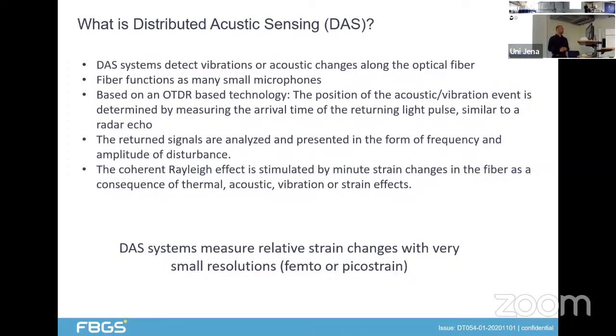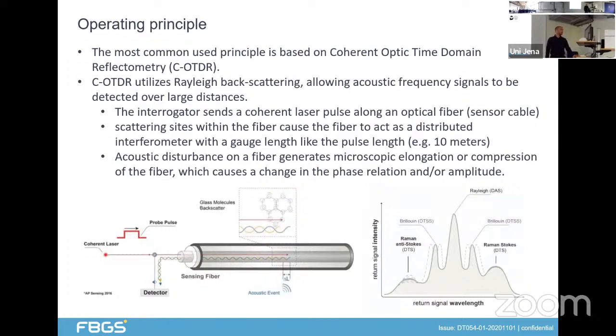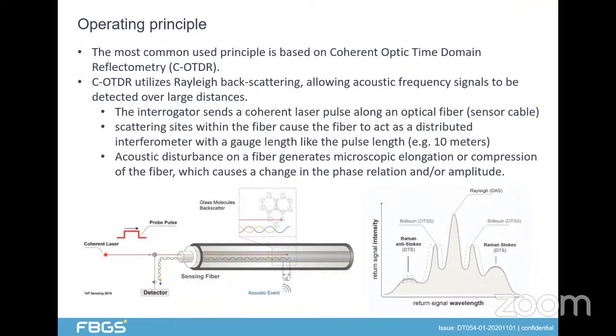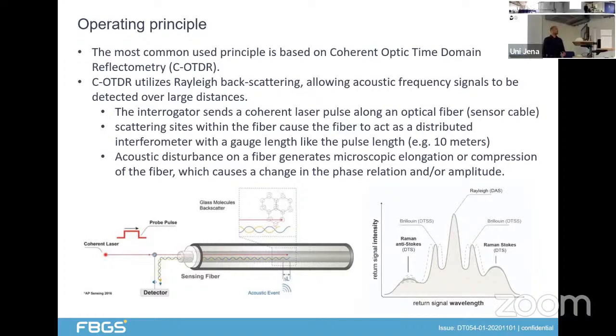The good thing about DAS systems is that they have really small resolutions. They can pick up strain, so changes in the fiber, in the range of femto or picostrain. On the other side, it is hard for these systems to evaluate absolute changes. So usually they can just measure a relative change. What is the operating principle? Usually this is based on coherent optical time domain reflectometry. That means a coherent laser pulse is coupled into the fiber, and then the light scattered by the fiber itself is detected.